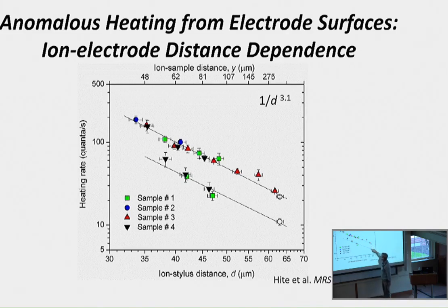Cleaning from here to here. It was already clean, okay? When we first put the trap in, it's up there. And then we cleaned it. Then over months it actually rises up a little bit, so we cleaned it again just to try to get it better. That's from accumulation of stuff from the vacuum sticking to the surface. So in the clean line, one of the samples was clean and one was not.